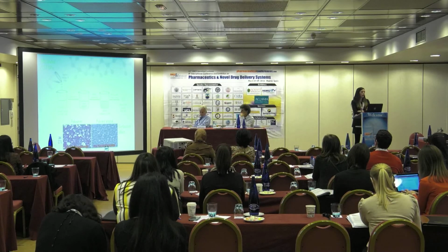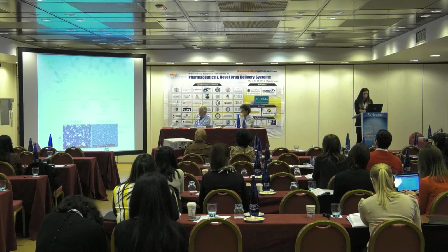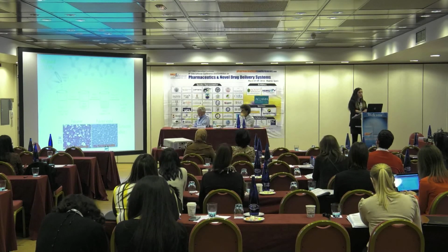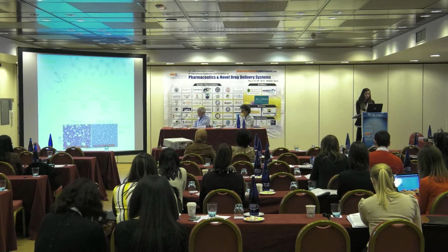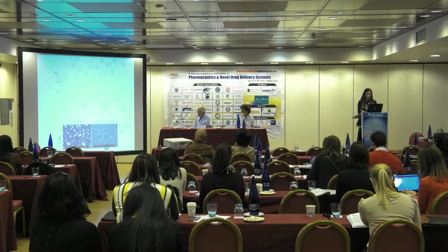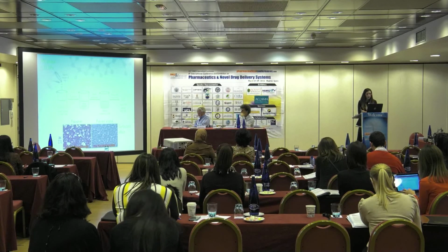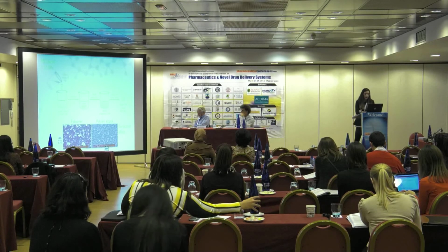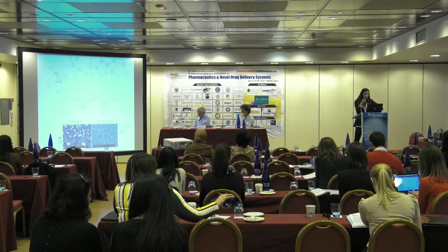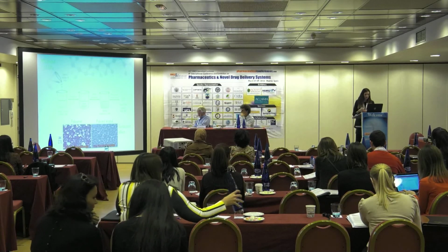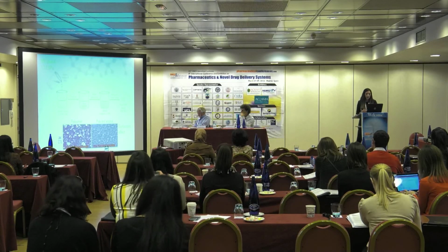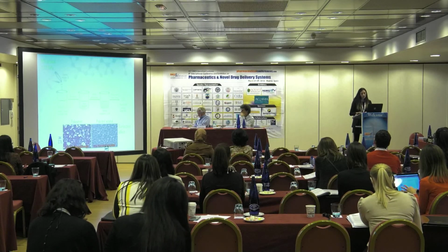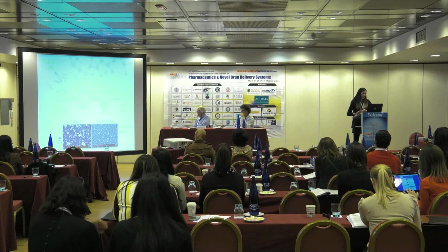Finally, we also work with an oncologic agent, tamoxifen, and the interesting thing is that we could study a different drug regarding the hydrosolubility. It's a hydrophobic drug, so in this case we use a simple emulsion with the solvent evaporation technique, so we only have to make one emulsion. We always use sonication to make the emulsions, and we use PVA as a surfactant. Another interesting thing is that in this case we tried to compare different surfactants, and we also tried poloxamer, but in this case it was not good for us, so we decided to continue with the PVA, the polyvinyl alcohol, and with this surfactant we can get really monodisperse particles.